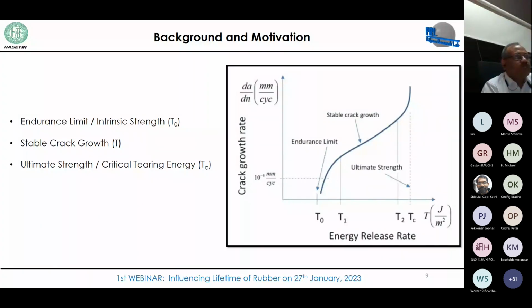So that starts with the endurance limit T0, which is also called the intrinsic strength, then the stable crack growth zone, the steady state zone, and ultimate strength or critical tearing energy. One important point which I must mention here, and Dr. Robertson has also mentioned, is that the endurance limit, intrinsic strength, was not talked about much in the literature. Maybe in 1978 Lake and Yeoh, and later Professor Bhowmick gave some of the things, but due to the unavailability of the proper instrumentation, it was not explored so far.